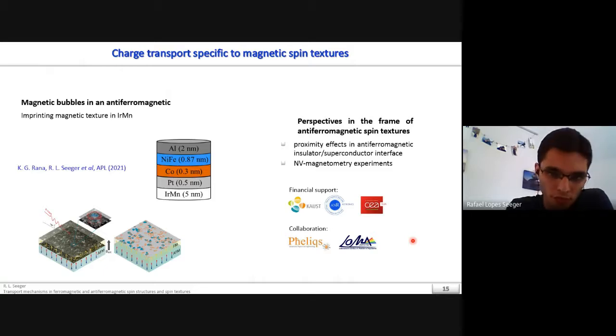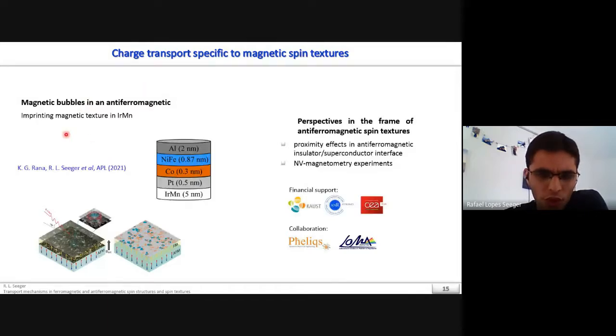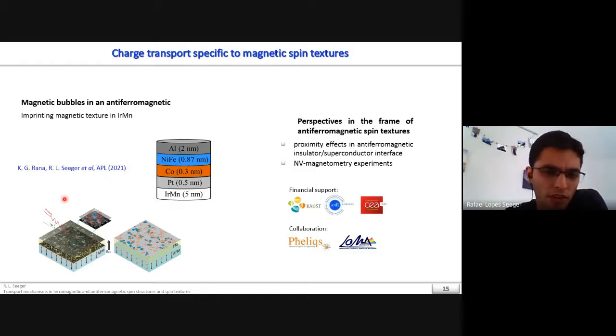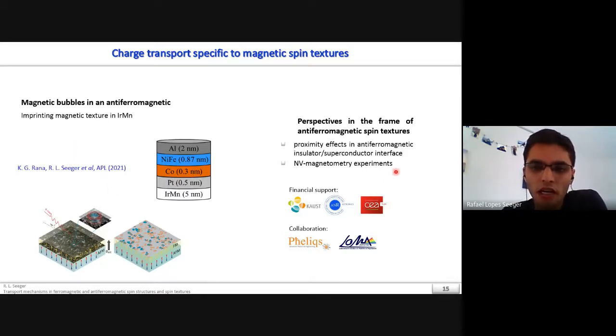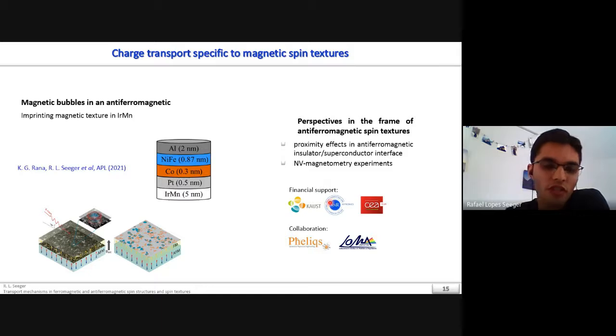Before concluding this section on magnetic spin textures, I will mention another study we performed searching for spin textures in iridium manganese using an XMCD approach. We optimized the stacks for performing these experiments and were able to measure some spin textures within the IrMn layer, where the signal came from the uncompensated manganese spins. As a perspective in this project, there are attempts to study proximity effects in anti-ferromagnetic insulators close to a superconductor, and to do NV-magnetometry experiments to directly observe the imprinted textures in IrMn.